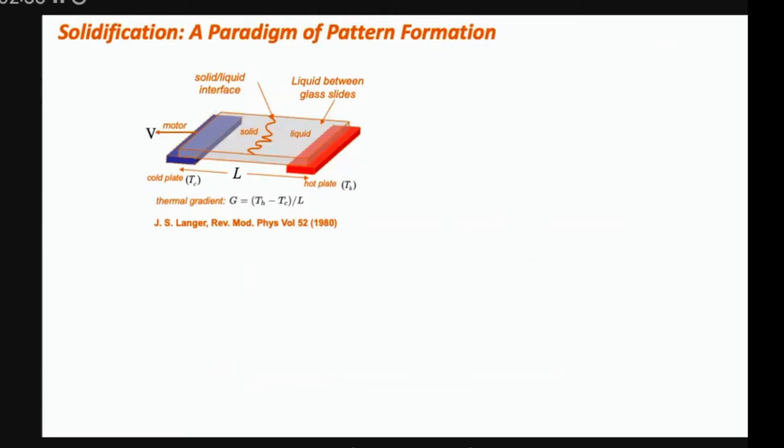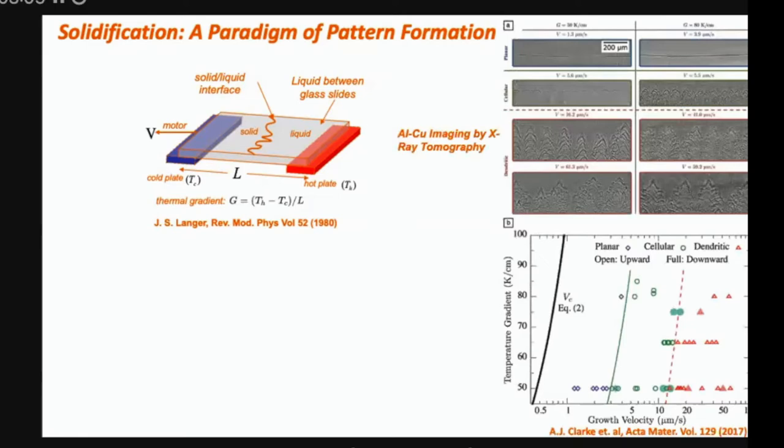So here's a kind of go-to experiment that people have been using forever to model pattern formation in solidification. And it is, in fact, a paradigm for many other types of patterns, not just solidification. The idea is you have a microscope slide with some fluid in it, and you put it on a stage that comprises two hot plates, and then you move the slide containing the fluid to the left, and you're essentially pushing it through a thermal gradient from where the hot liquid gets to go to the cold side, and eventually it starts to crystallize, and an interface develops, and it starts to move, and patterns start to emerge on this interface.